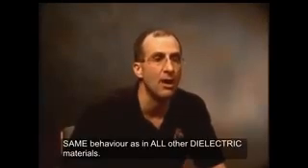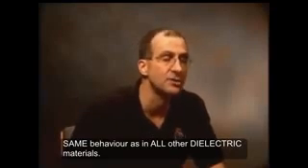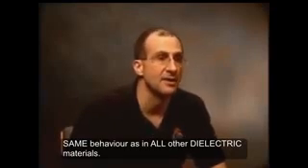And then as time goes by, as weeks go by, here they are after about 3-4 weeks, you see these large chain agglomerates, centimeters on an edge, made up from 5 micron diameter mica flakes. So even in a system with particles as small as 5 microns, with a surrounding fluid of the density of water, we see the same kind of behavior as we did in the sodium chloride, the sugar, and the coffee.